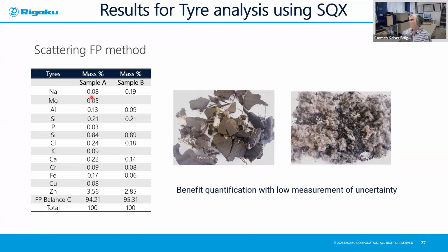This material contains minor elements from sodium up to zinc. As I mentioned, tires contain a lot of zinc, and as we saw earlier, the zinc will influence the process. So it's very important that we get a good analysis from this material. My recommendation to analyze this properly is to make several measurements from this very heterogeneous sample.